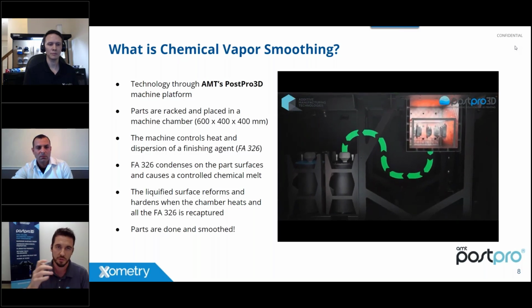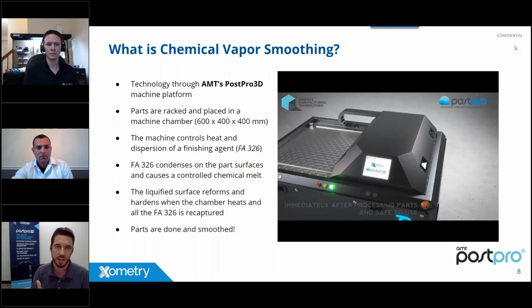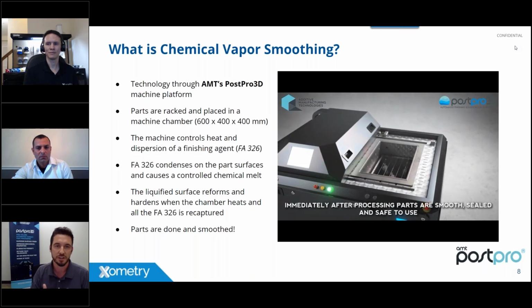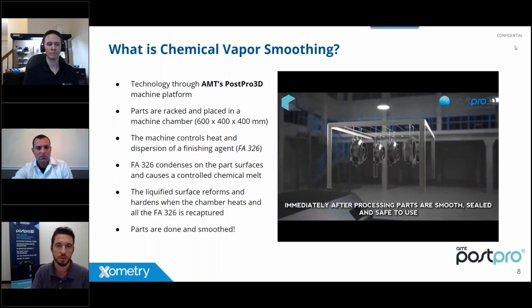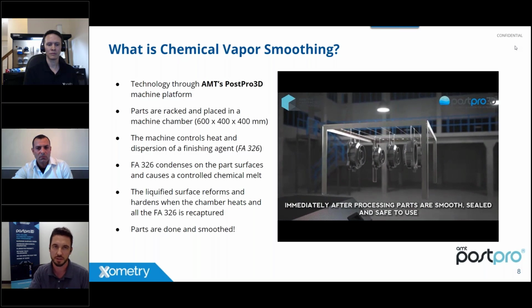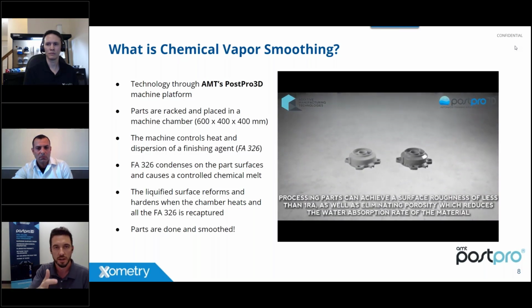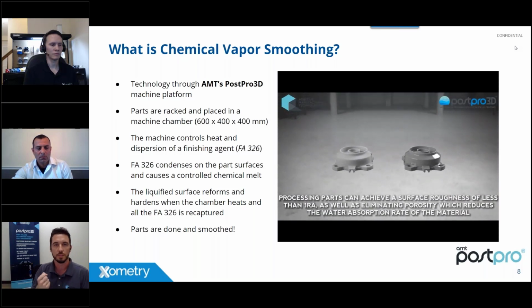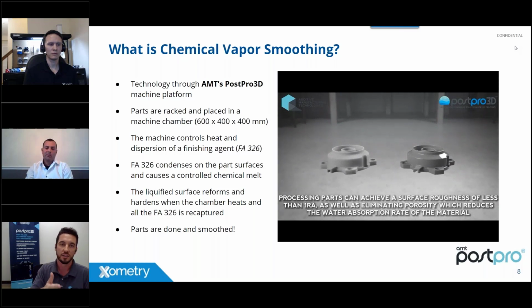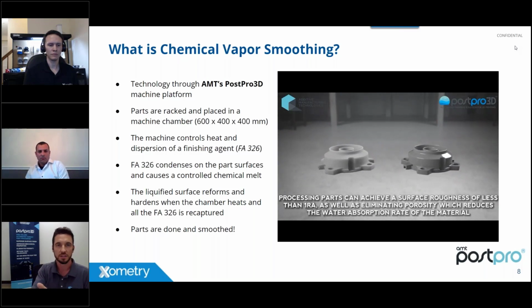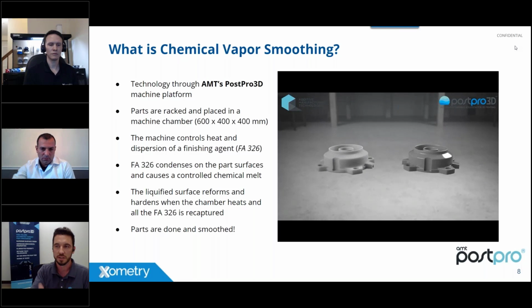And then we have to carefully stop that flow state before we start rounding out features. So that, again, is very important when we control that process as well. And then we re-harden that polymer and extract the chemistry out, and at the end you have a completely processed part with no added or removed material.